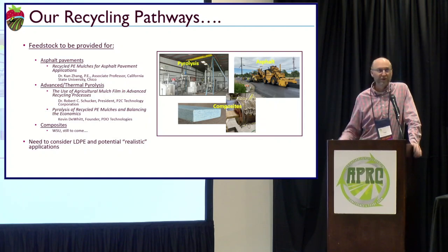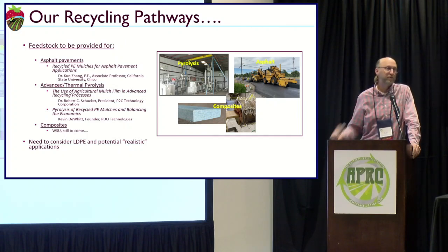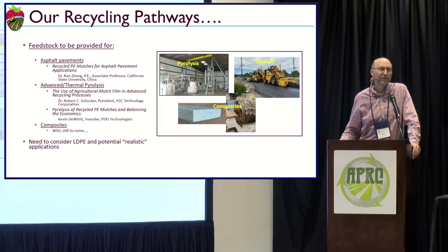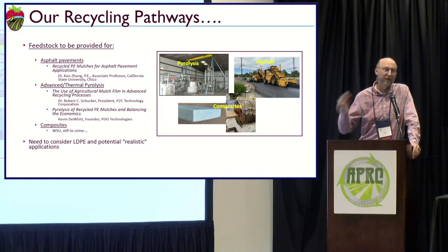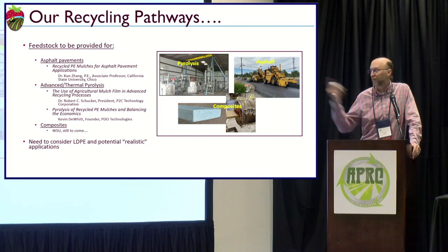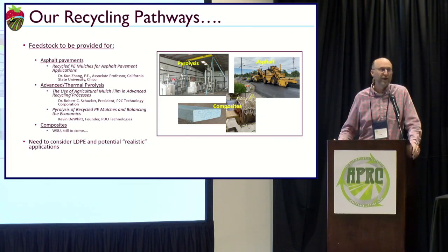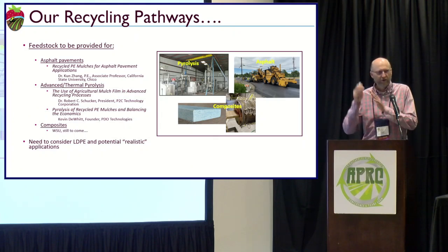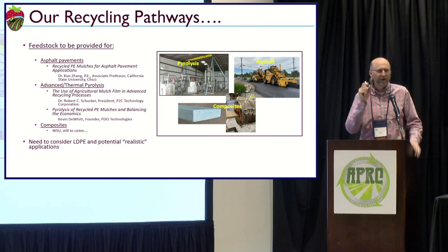It's a great material for making packaging, but it's really hard to take a recycled material and turn it back into a blown film that LDPE is commonly in. And so finding the right type of second end use, the durable goods or the pyrolysis or the asphalt, is not the easiest thing to do when you're dealing with these kind of materials. There is a lot of effort that goes into making an LDPE in a virgin form to blow mold that. It's cheap, but there's a really tight processing window in there.